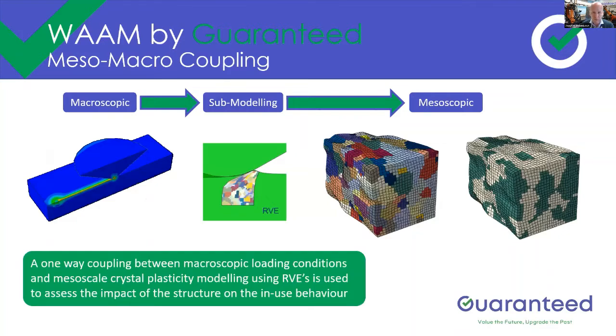And the last element in that chain of simulation is to understand, if we take that predicted microstructure and load it with the real-life loading conditions that the component is also going to see in real life, how is the part then going to behave? And this is done by creating a representative volume element and submitting it to a crystal plasticity model in order to understand how that microstructure is going to respond to the actual use case, to the actual loading conditions, and then to optimize that entire chain.